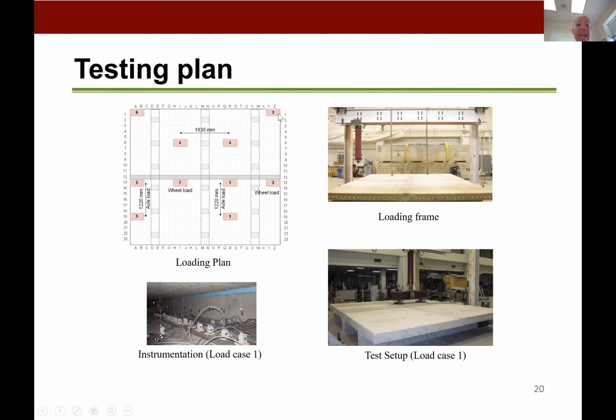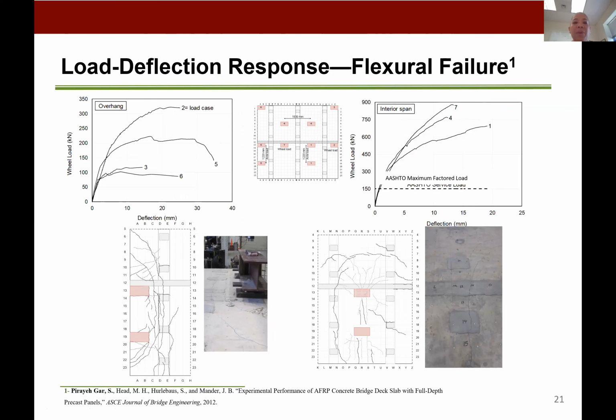We also loaded on the edges as well as on the interior side by side for our wheel loads. Then again on the overhang, trailing wheel loads on the overhang, then going back to the corner and then the interior wheel load 7 of a single load. So we had a lot of instrumentation, as you can imagine. We had one single ram applying the load through a spreader beam so that we could mimic our wheel load cases. So moving on, we were able to test the bridge deck, and we got some results that were very encouraging.